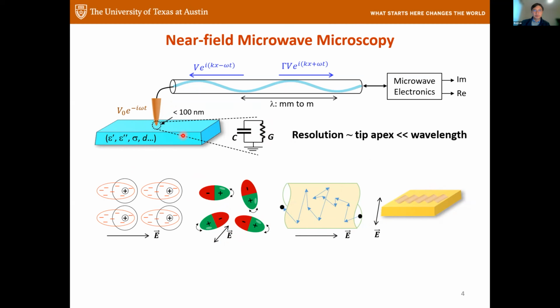And the pros of this technique is that the measurement is completely non-invasive. So we don't really need to put any electrodes, don't need to make any devices on the sample. And we directly read out this information with some prior knowledge of the sample. And we can also do subsurface imaging, because the coupling is dielectric, so we can easily see through, let's say, 20, 30, even 100 nanometers of dielectric. Right? So both of these are fairly unique, I would say, which allows us to measure quite a bit of materials that I will introduce later.